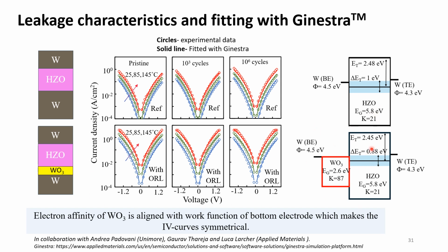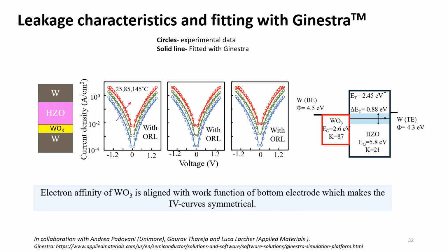There is a lot of detail going on here, but what I would like to talk about is this slide. Here you can see in the band diagram of the tungsten oxide layer that the dielectric constant of the tungsten oxide is 87. Another interesting thing here is that although we have an asymmetric device structure for our ORL device, meaning we have tungsten oxide only at the bottom but not at the top, still the IV characteristics are pretty symmetrical for this device. This is happening due to the band alignment between tungsten and the tungsten oxide layer. You can see here that the electron affinity of tungsten oxide is getting aligned with the work function of the bottom electrode, for which we are getting symmetric IV characteristics for this ORL device.